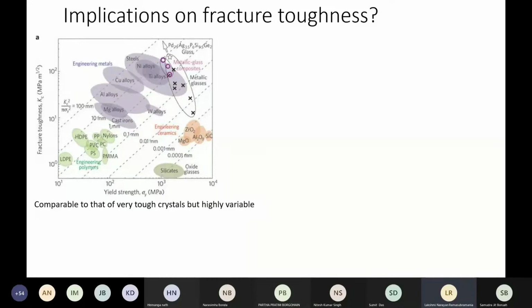At least they are very close to that of your conventional alloys, and also have very high yield strength. So it is a very rare material where you have high yield strength and fracture toughness. Unlike ceramics, if you look at ceramics, ceramics only have very high yield strength. Let us look at ZrO2, MgO, as well as aluminum oxide. You see, they have very low fracture toughness, probably like 1 MPa root meter, but they have very, very good yield strength. So metallic glasses can actually be an interface, or rather better materials than both ceramics and metals. And that is why these metals are considered very nice.